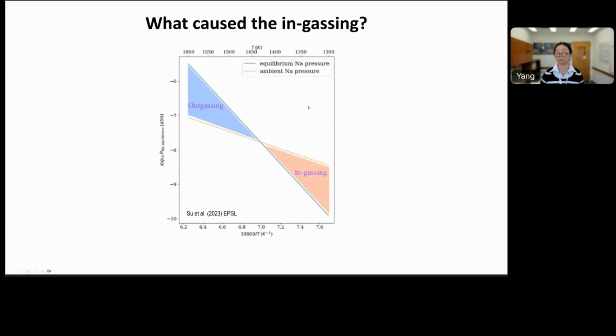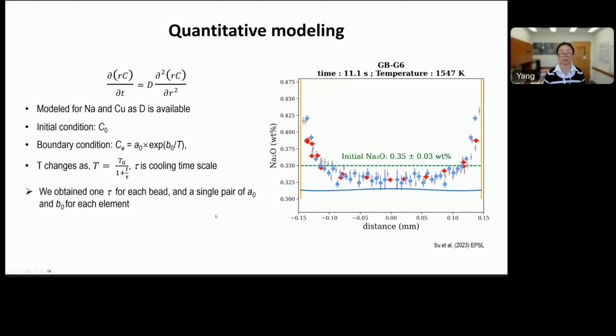The solubility of volatiles is a temperature-dependent function. When we first erupt at a higher temperature, the dissolved sodium is higher than the sodium in the ambient gas, so we see outgassing of sodium. But when the temperature cools, the pressure in the ambient gas is actually higher than what we have in the melt, or in the glass bead, so we see this kind of diffusion back into the bead. And Xue created this fabulous diffusion model, and we can model this outgassing and in-gassing trend with just a single equation and 3 unknowns.